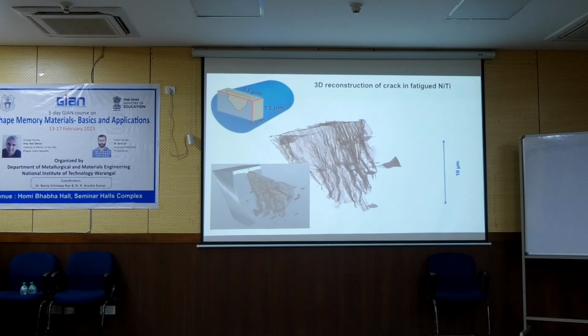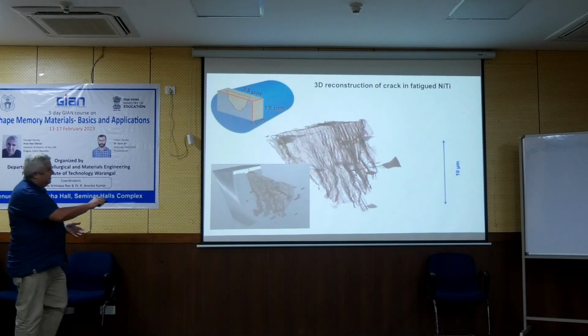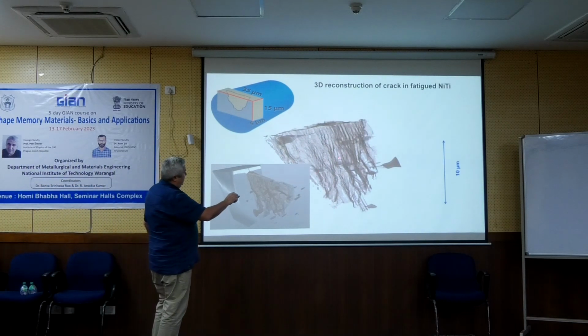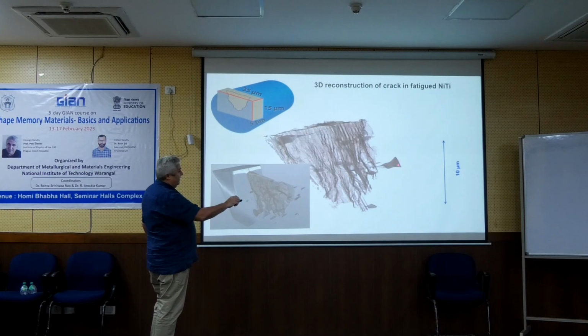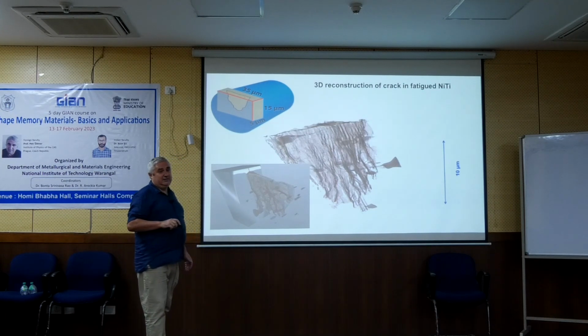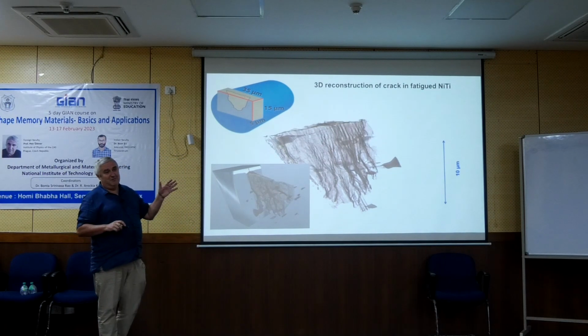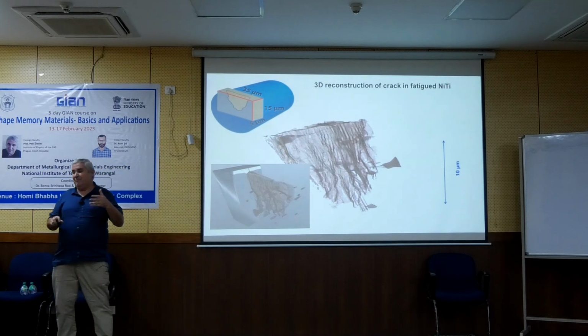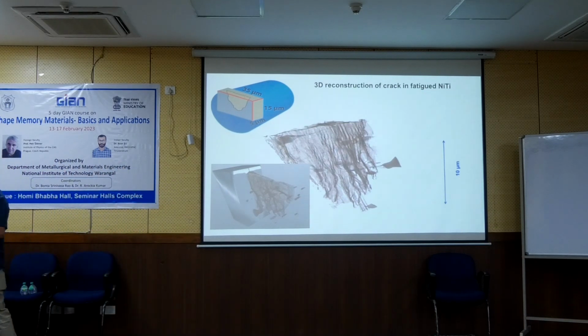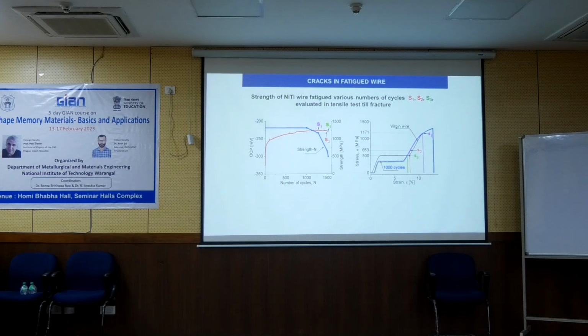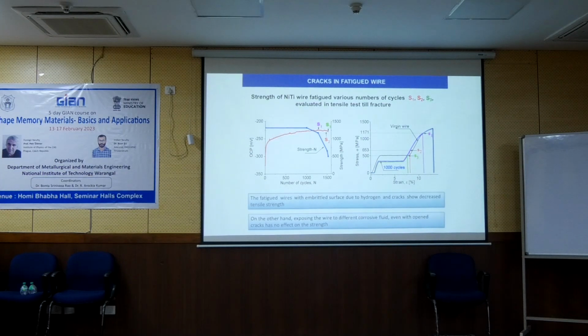And these things around here, this is the carbide and oxide particles which are around, and there are really many. One of the results of this SEM-FIB observation is that the density of the oxide is very high. So when this medical company saw what kind of oxide density they have in the wire, they were really terrified.